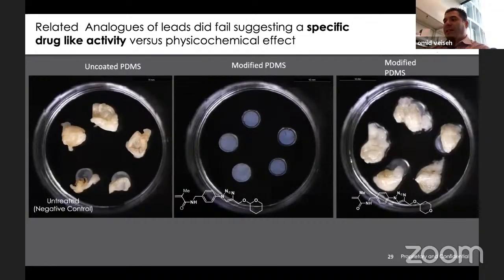And the other reason why we think they have drug-like activity is because, again, these discs, when they're unmodified, initiate an immune response. When we attach the small molecule to it, the body doesn't recognize them as foreign, and these discs come out clear. But if you look at this oxygen group, when we created an analog whereby we moved that oxygen group to this position, it entirely killed the activity of the molecule.